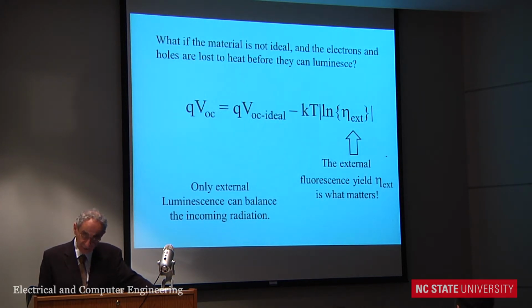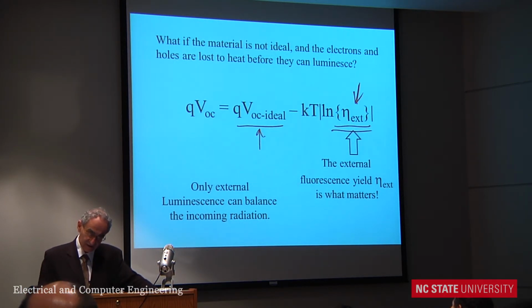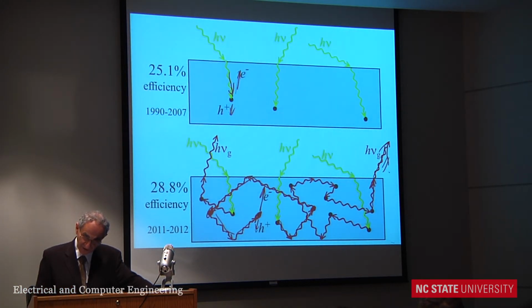And indeed, this is what Shockley told us. Maybe not in so many words, but this is what he meant: you'll get your ideal voltage, but only if it is accompanied by perfect luminescence, to say for every solar photon, you end up emitting light. And if you fail to achieve 100% external luminescence, you will not get the ideal voltage. And if you achieve 1% luminescence, well, you'll lose natural log of 100 times kT. You lose 5 kT. So it's quite significant. And also, since it's balancing incoming sunlight, it doesn't matter what's going on internally. You have to have some external fluorescence. And that's why I said you need some of the light escaping externally.